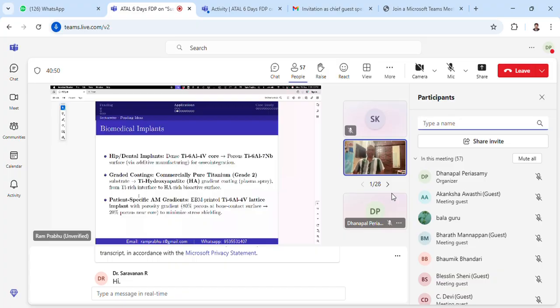your hip dental implants, if you go back and see, presently people use only a single material Ti64, but in research perspective, you can have dense core of Ti64, titanium 6 aluminum 4 vanadium. On top of it, you can have a porous structure of titanium 6 aluminum 7 niobium. When you have a porous surface and when you integrate into your human body, the porosities will act as a space for the human tissue to grow.